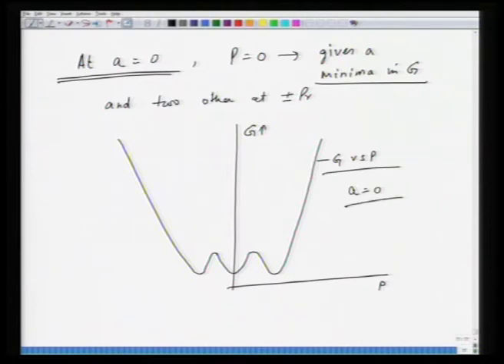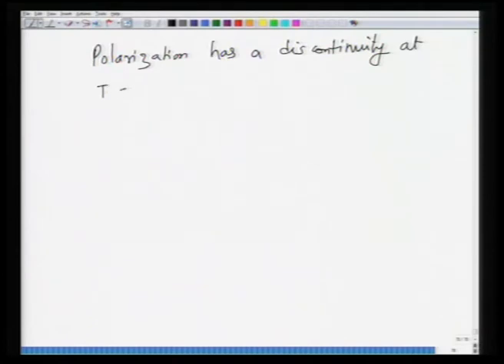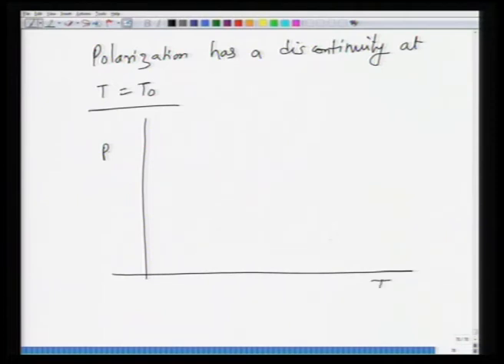So this is G, at A equal to 0, which means that polarization has a discontinuity. This kind of transition also means that polarization has a discontinuity at T equal to T naught, and basically what it means is that when you plot polarization versus temperature, in the second order case the curve is continuous, but in the first order case polarization goes like this and then suddenly drops to 0.